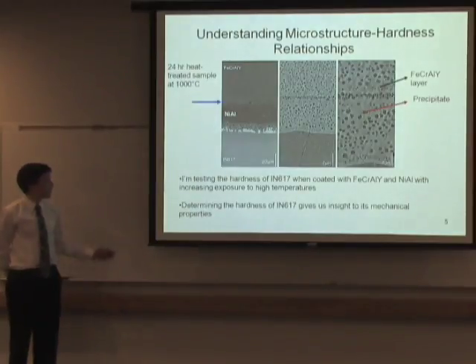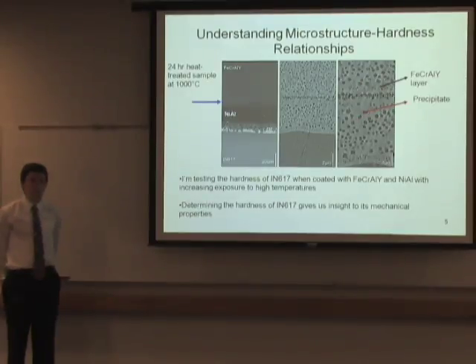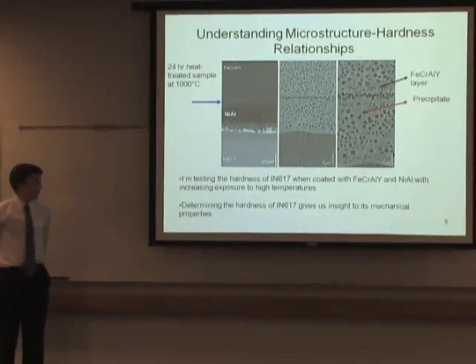So here is a heat-treated sample of Inconel, and if we zoom in on the FeCrAlY layer right here, we can see these tiny small precipitates start to form due to interdiffusion. And we don't really know, or we didn't really know, how that would change the hardness or other mechanical properties. So what I have done is I've been measuring the hardness of Inconel when coated with these two alloys, because the hardness will give us insight into some of the mechanical properties of our sample.